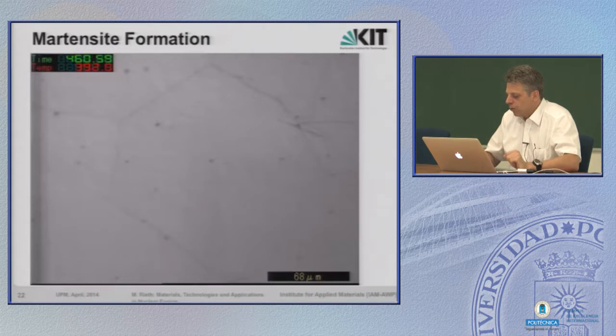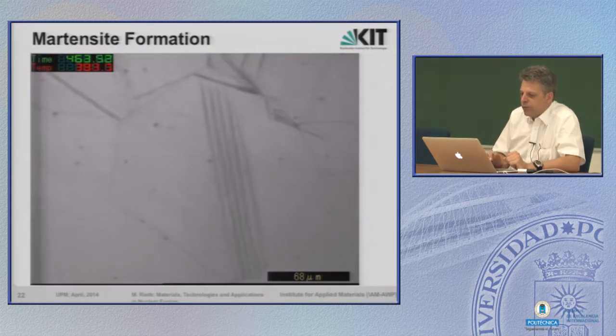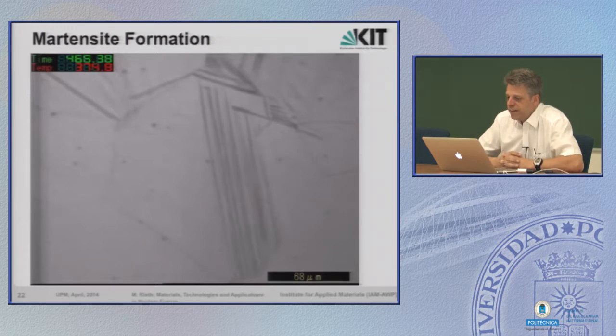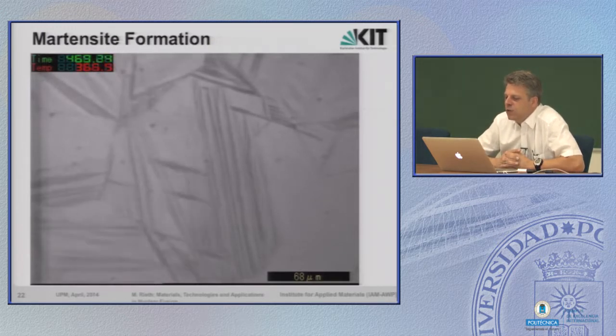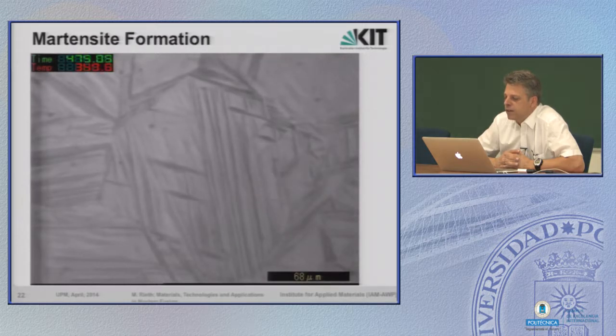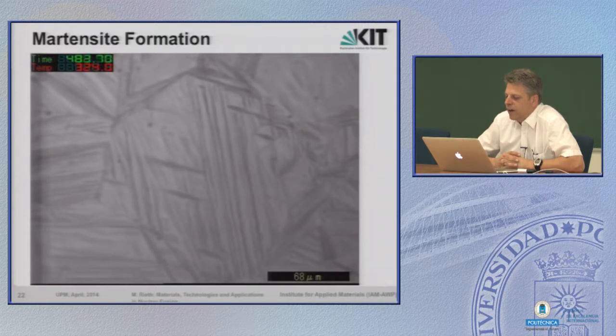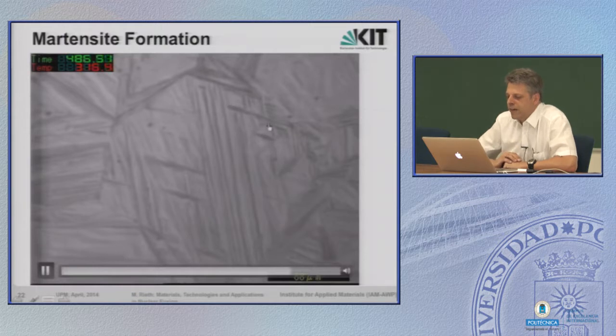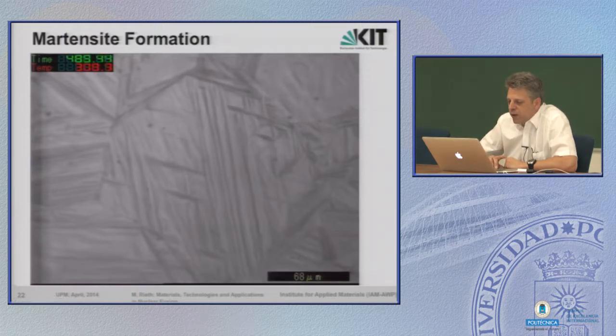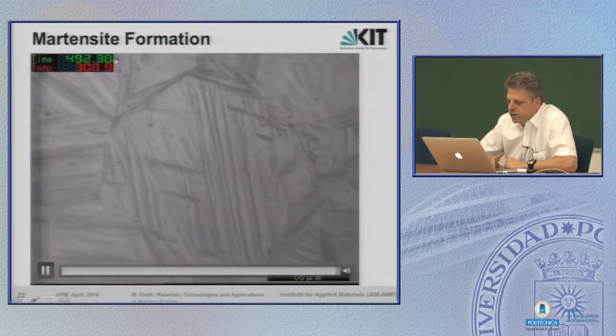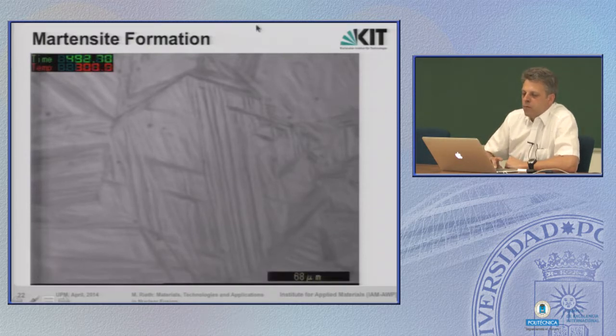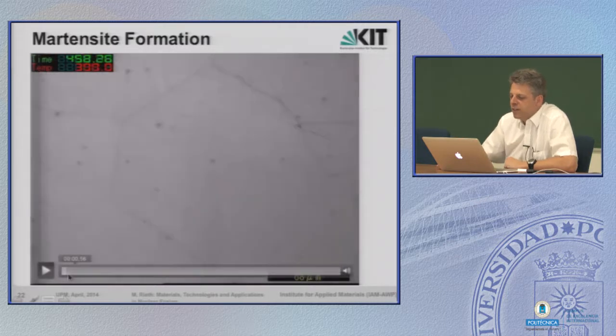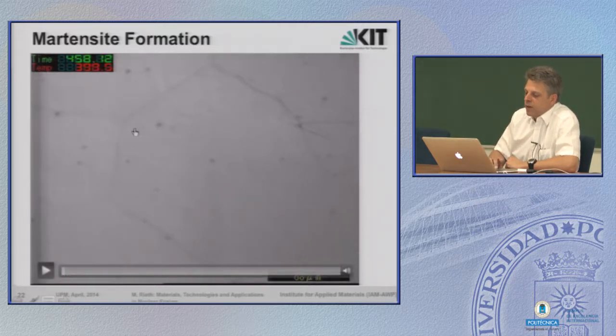So far, that's all basic theory, but I have seen a very beautiful video where you can see in situ how this martensite forms, starting from an austenitic structured steel. And you see, formerly we had the austenite grains, and then very quickly we get some features inside this grain. And well, temperature comes down here to 300 C, and this is where we end up during the transformation.